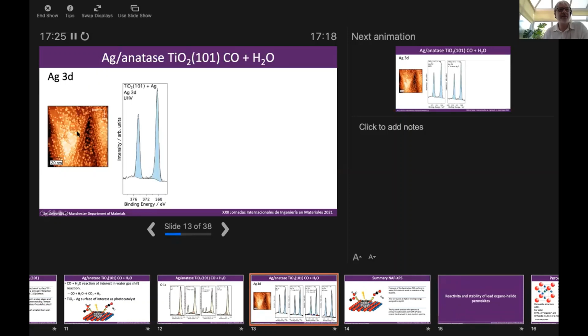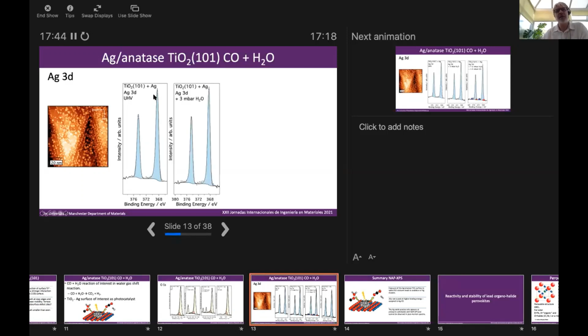So this was the coverage of silver we were using, and this is the clean UHV measurement of the silver 3d peaks that we saw earlier. There's nothing spectacular there. It's exactly what you'd expect. The peak shapes are metallic-like, very narrow, and the binding energies correspond to metallic silver clusters. When we let in water, again, there's very little change. We don't see any changes in the structure of the silver 3d. There's no oxidation. So again, fairly boring, and it seems to suggest that the hydroxide that we saw forming in the previous spectra in the oxygen 1s is simply due to reaction with the titanium dioxide terraces.